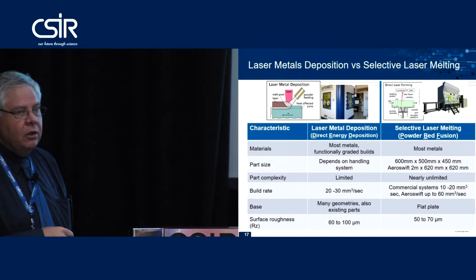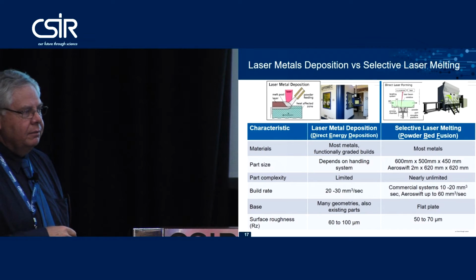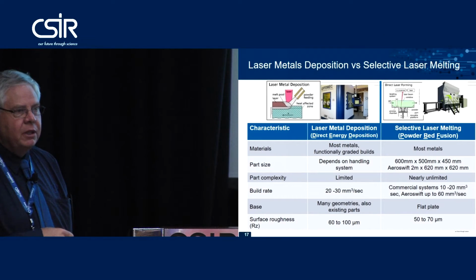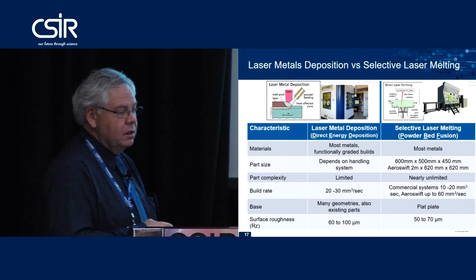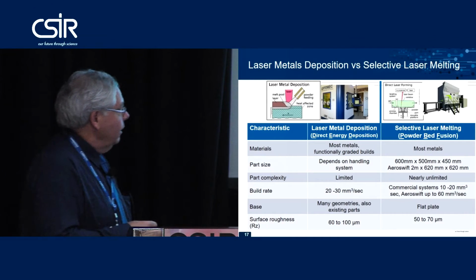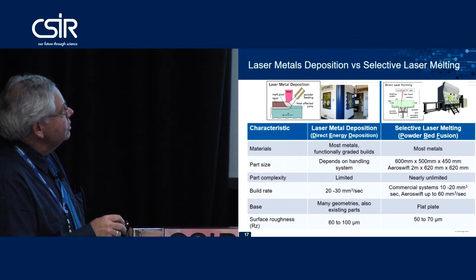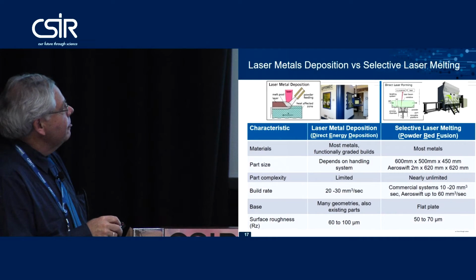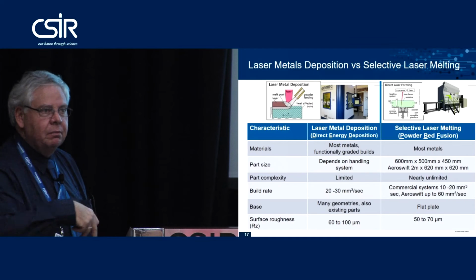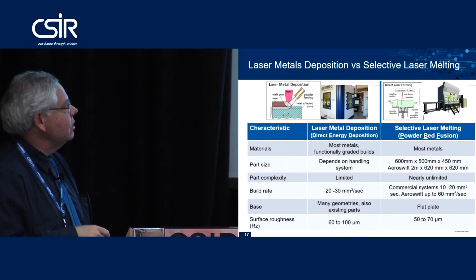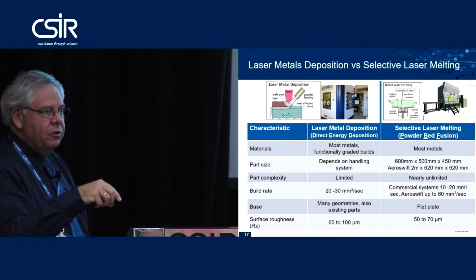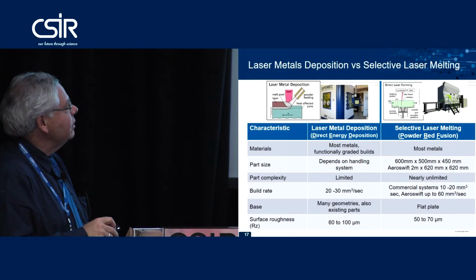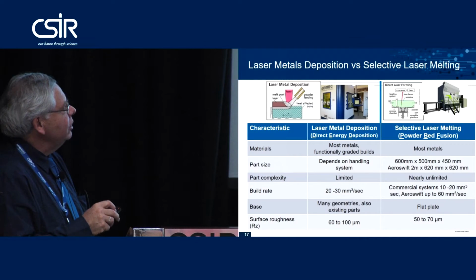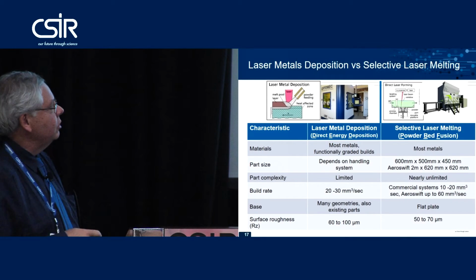Maybe just to touch quickly on the two technologies which is important when you think about 3D printing or additive manufacturing in the metals industry. This is the Aeroswift process, which is called the powder bed fusion process. In this case, you have a thin layer of powder which is then consolidated or welded where the laser beam basically touches the powder, so the laser scans across the powder bed surface. After you've consolidated the first layer of your component, the bed drops and you deposit a new layer of powder and you do the second slice of your component.